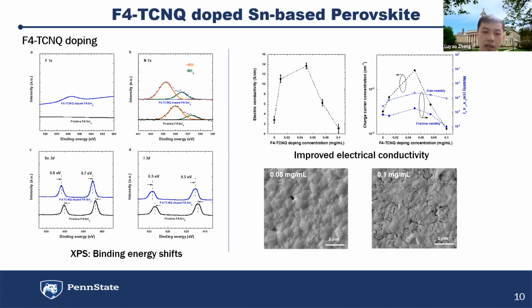material is really inside. And then we found that there are very large binding energy shifts, indicating the chemical environment of these elements has changed after introducing the F4-TCNQ. That indicates the F4-TCNQ really doped into the perovskite and made some changes. And then we measure the electrical conductivity.